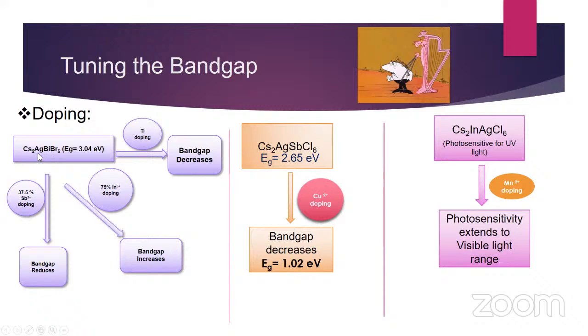For Cs2AgBiBr6, it has a band gap of 3.04 electron volt. If you do thallium doping, you get a decrease in the band gap. If you dope it with 75% indium ions, you get an increase in the band gap. And if you dope with 37.5% antimony cations, you get a reduction in the band gap. Why is it important? Since the band gap is decreasing, it increases the carrier lifetime, and it is good for application in devices, such as solar cells. And here is another example.